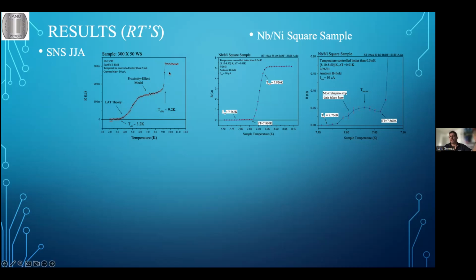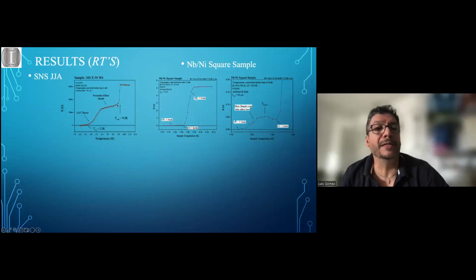So imagine you have gold that connects one end to the other, and then on top there are chunks of niobium crosses that can be resistive, but then at some point they will become zero. The resistance will become zero. So this is the first sharp drop that we see here, right at the temperature when the niobium becomes superconducting.